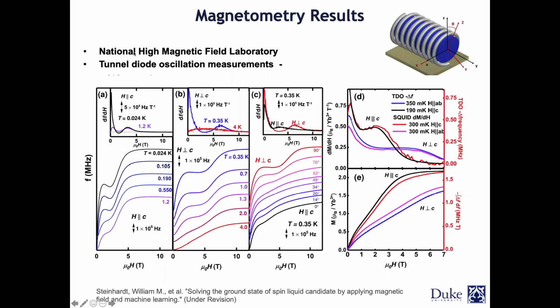Magnetic Field Laboratory in Florida, and we used a technique which is very sensitive. This technique is called the tunnel diode oscillator technique. In simple words, imagine this blue is our sample. We put it in a coil, and then we look at the resonance frequency of the coil. If the magnetization of the sample starts to change, then the L for this coil, this is an LC circuit, also starts to change, so the frequency starts to change. This is how the physics of it works.